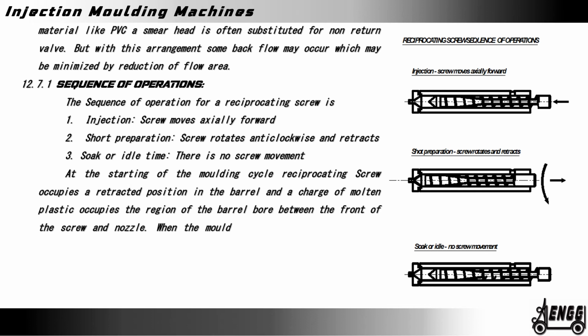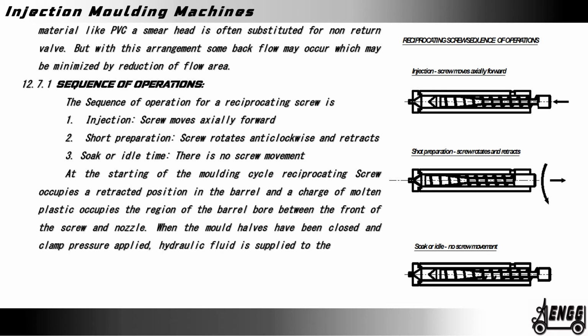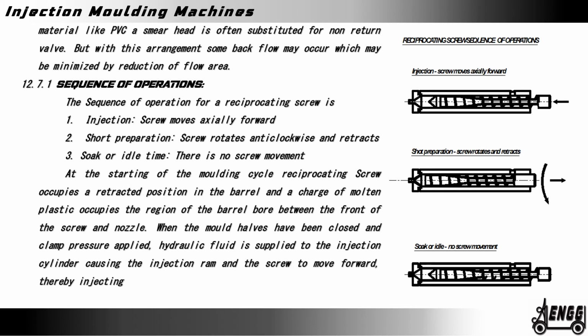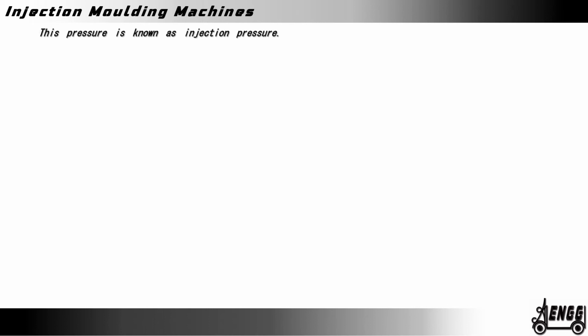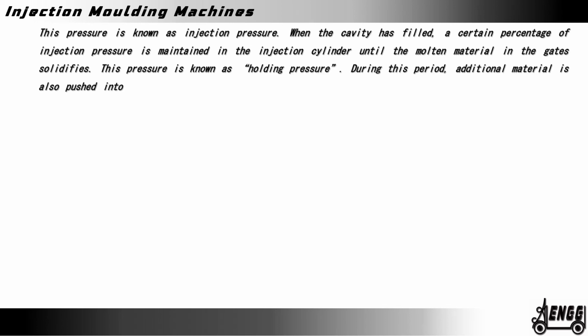When the mold halves have been closed and clamp pressure applied, hydraulic fluid is supplied to the injection cylinder, causing the injection ram and the screw to move forward, thereby injecting material through the nozzle and into the cavity. This pressure is known as injection pressure. When the cavity is filled, a certain percentage of injection pressure is maintained in the injection cylinder until the molten material in the gate solidifies. This pressure is known as holding pressure. During this period, additional material is also pushed into the cavity, known as packing the cavity, in order to compensate for the shrinkage to a certain extent.